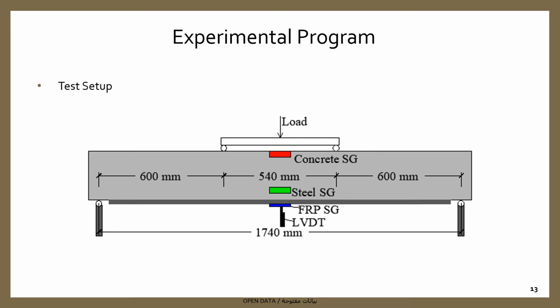All beams were tested under 4-point bending in a displacement-controlled mode at a rate of 2 mm per minute and a shear span of 600 mm. An LVDT was placed under the beam's midspan to capture the deflection of the beams. Moreover, strain in the concrete and steel was monitored by placing strain gauges at midspan on the top of the concrete and on the bottom of the steel reinforcement bars.